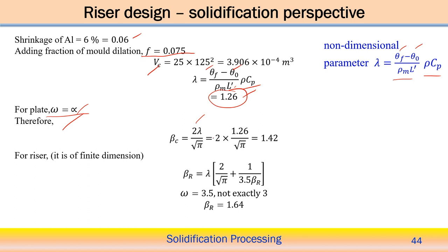So, beta c is calculated as 2 lambda by root pi. From here you can calculate, this is 1.42. So, this is the beta c for the cast volume. For the riser it is not of infinite dimension, and the beta value can be different because it does not have a flat surface. It is a cylindrical volume. So, omega value in this case can be 3 or 4, between 3 and 4. We are assuming omega to be 3.5, not exactly 3, because it is not an infinite dimension; that is why we consider in between 3 and 4, that is 3.5.